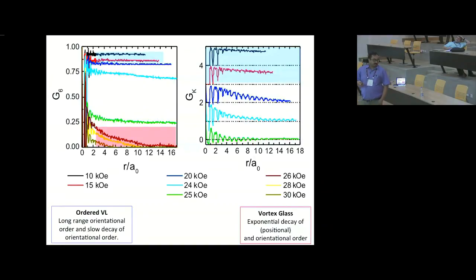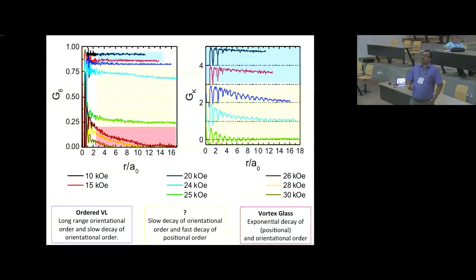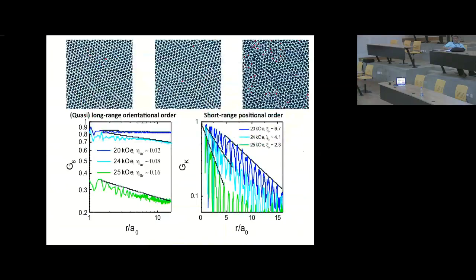The interesting thing that we see: these two regimes were always speculated to exist, but what we see is something in between, where you have a very slow power law decay of orientational order, which means you have a quasi long range orientational order, but an exponential decay of positional order. So this is exactly what you expect in a hexatic state, a state characterized by long range orientational order, but no long range positional order. Now in 2D this is called a hexatic state. Since we are dealing with a 3D system, to contrast it, we call it an orientational glass.